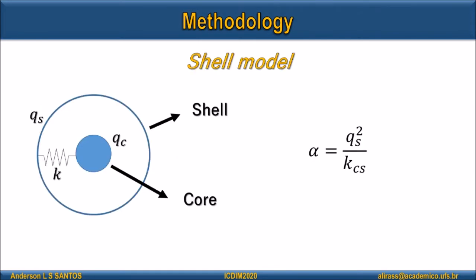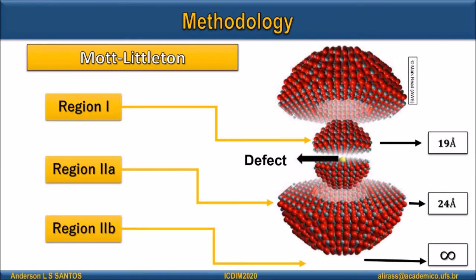And the electronic polarizability effect was included using the shell model of Dick and Overhauser. This approach consists in dividing the ion into two parts, whereby a core represents the nucleus and inner electrons of the ion, and a shell simulates the valence electrons. And the Mott-Littleton method was used to calculate the defects in the structures, which considers the solid divided into two spherical regions, where region 1 is treated explicitly and the positions of the ions are freely moved to achieve the low energy configurations, while in region 2 the chemical species are treated using a quasi-continuum method. This methodology has already been successfully applied in several works for different materials.